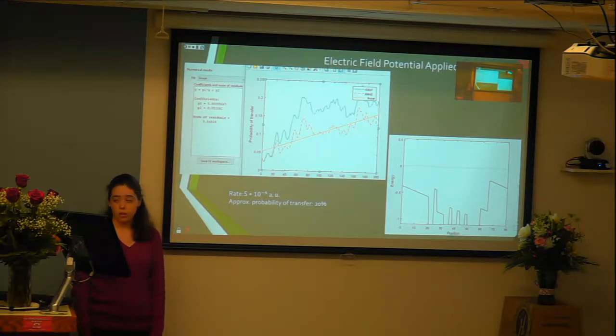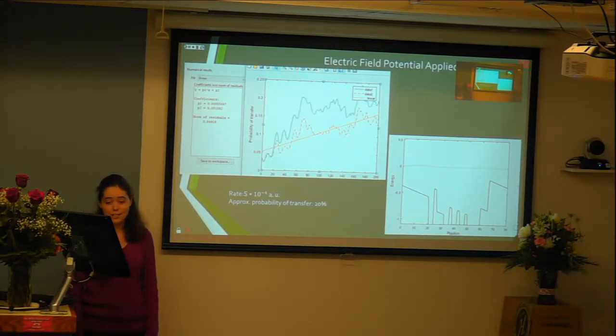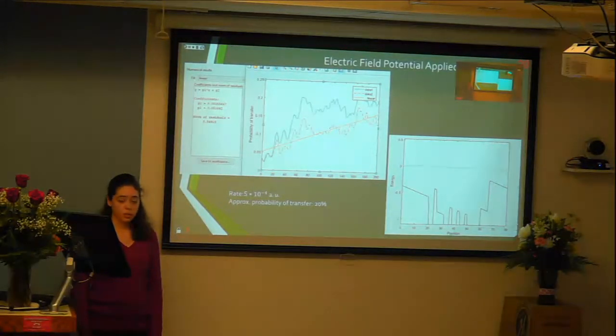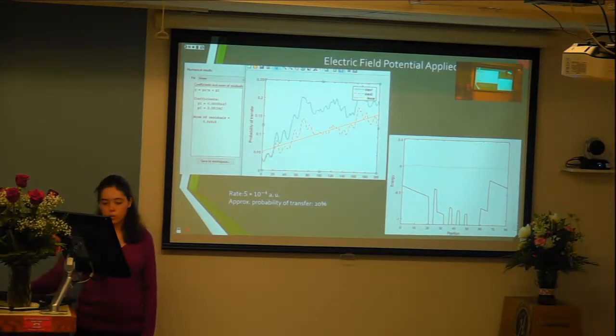And this was at an electric field strength of 0.01 AU, which you cannot see because it's behind the video. But the data 1 and data 2, so the blue line and the red line, represent the two different methods. And the yellow line is a linear slope to determine the rate that was obtained. P1 being the rate, and in this case 5 times 10 to the negative 4th, with approximately a 20% transfer.